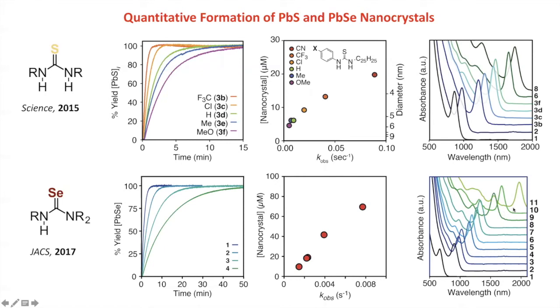As you go out to large sizes and long wavelengths, notice how far this excitonic transition is from this one and that one. Those are big spacings. And the visibility of those spacings is partly related to this line width. Okay, so the line width of these features is really narrow, and that's really powerful for doing model studies.